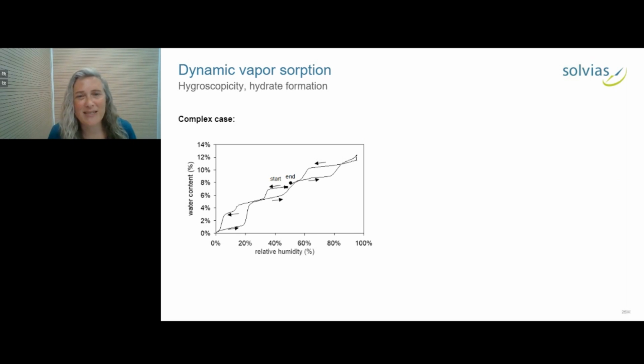Dynamic vapor sorption is another very useful method. And this is also a method where you take a microbalance, put your sample on it, and expose it to different relative humidities, either in a ramped or in a stepped manner. And you can understand things about different hydration states. So this diagram here is a real customer sample, and they started out with the dihydrate. And as we lowered the humidity, it converted into a sesquihydrate.